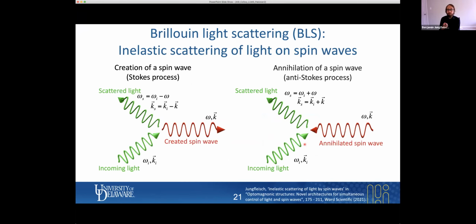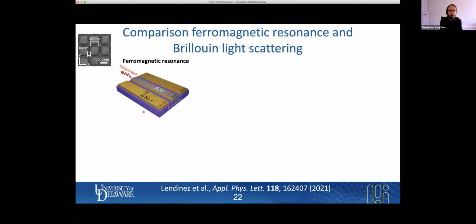The second technique here is Brillouin light scattering. That is based on the inelastic scattering of light on spin waves, or in the quasi-particle picture, of photons on magnons. And there are two processes, the Stokes and anti-Stokes process, which are the creation and the annihilation of spin waves. This process is energy and momentum conserving. So this means that the scattered light carries information about the probed magnons. And we can now analyze this very tiny frequency shift using a highly sensitive interferometer and get information about the magnons that are present in the system. So much about the background. Let me show you some of the experimental results.